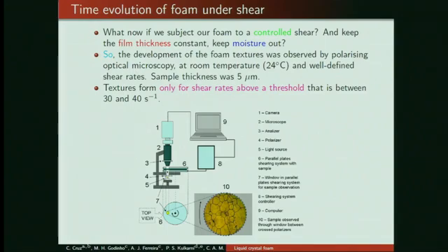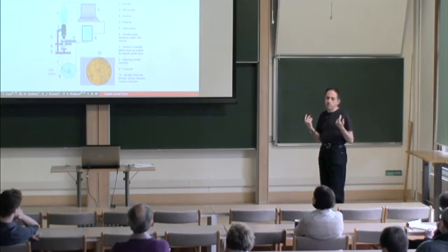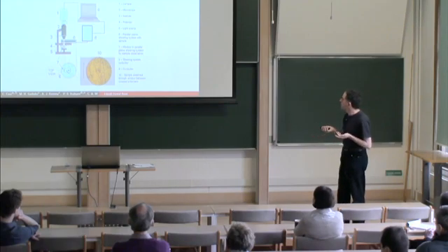This may or may not have been a factor in the results that we got, because, as I said, the original preparation was rather poorly controlled. It may be that the fact that we get a smectic at room temperature results from shearing. It may also be a result of the system sucking up some moisture from the air and undergoing a lyotropic-like transition into some lamellar phase.